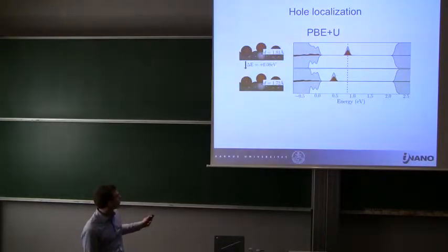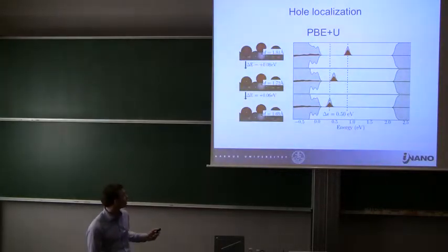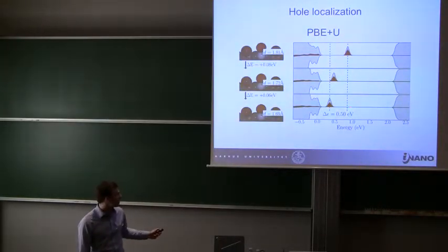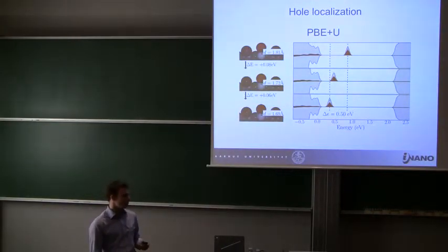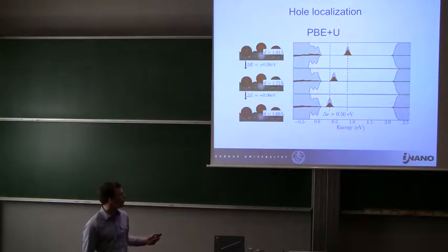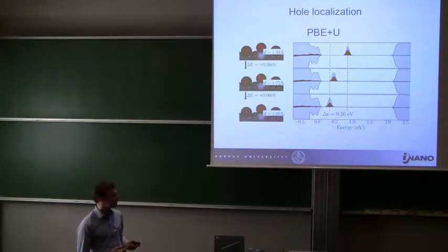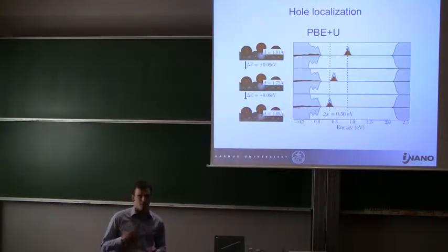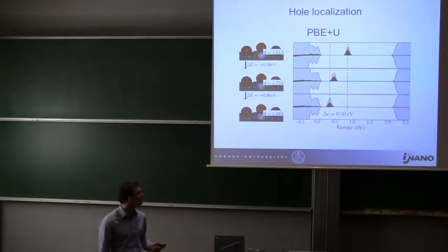What's more important is that the energy cost of doing this is very small. We can go a little bit further. We can move it actually half an eV closer to the valence band and only pay 0.14 eV to do this. So a small energy correction could bring the gap state down close to the valence band, and then it seems plausible that we could use a description where the hole is just at the top of the valence band. That is what we have done.